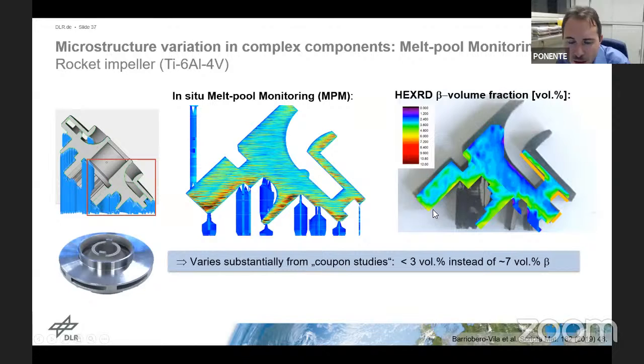And what we found is that, as expected, in the downskin regions, where the part gets particularly hot because it's over the powder bed and the heat cannot be conducted away from the part readily, there is an increased amount of beta phase, but it's only increased to like 6% or so, whereas the bulk of the part itself has only about 2% or 3% of beta phase, which is a lot less than we found in the cube that we produced separately. And this shows very readily that you have to be very careful with coupon studies and transfer to components.